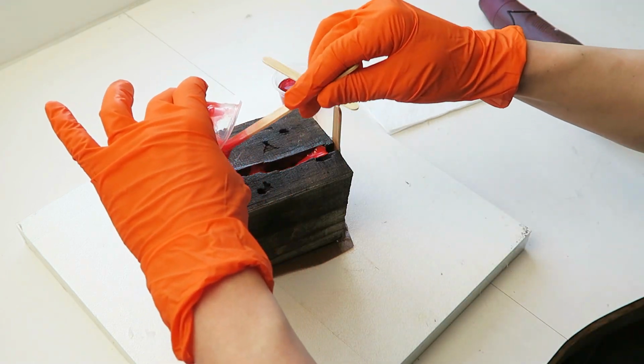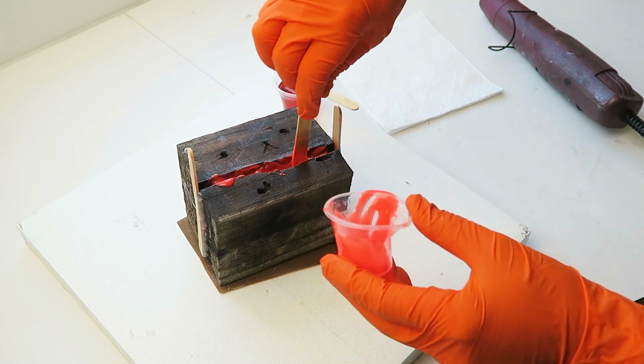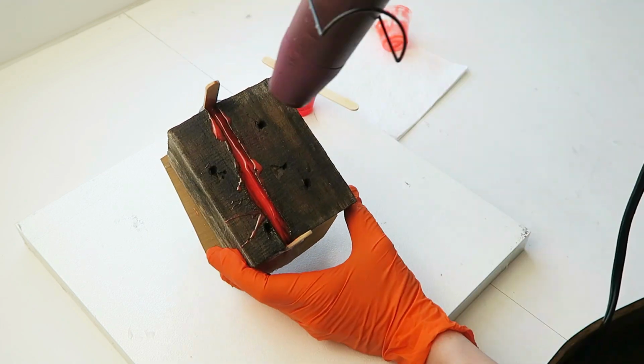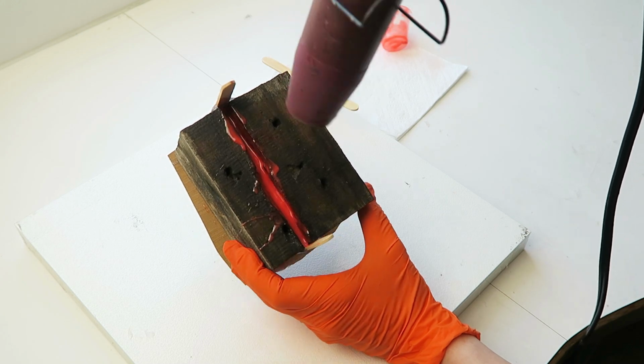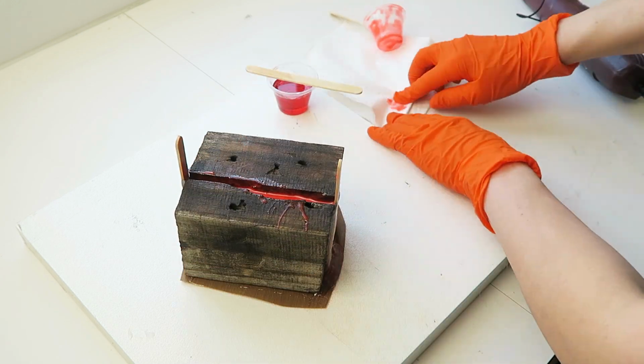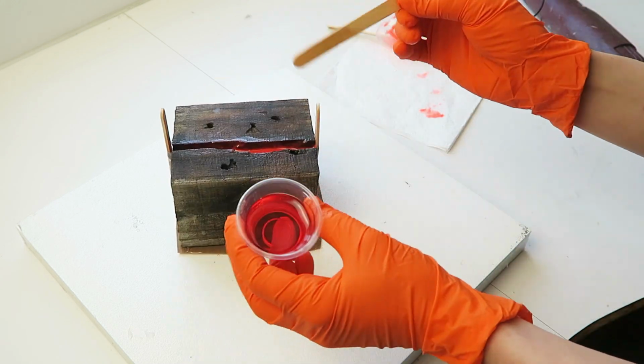To decrease the chance of leaking, I also once again let the resin partially cure before pouring. Although this ended up causing issues with trapped air bubbles that didn't have enough time to rise and pop before the resin cured.